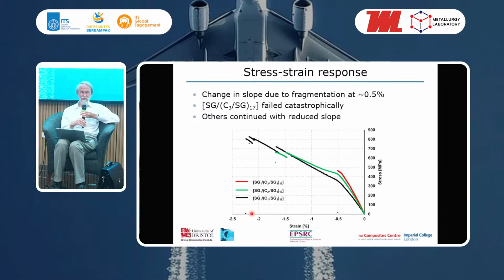So this shows a typical response for 3 different specimens with 1, 2, and 3 plies. The ones with 1 or 2 plies show this knee point in the stress strain response, and then they go to a much higher strain before eventually failing by delamination. But the one with 3 carbon plies together, in red, just gets up to this 0.5% strain, and when the carbon fibers fail, because you've got a thicker block of carbon, at that point you get a full delamination. So it fails immediately because the carbon is too thick. There's enough energy to propagate a delamination immediately.